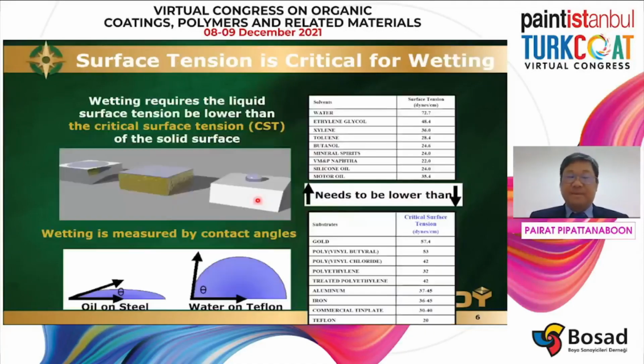This diagram tells you how the diluent or solvent has a surface tension in the unit of dyne per centimeter. And what is the critical surface tension or CST of solid surfaces, from gold, aluminum, iron. It is an example of some products, solvents and solid surfaces you can see from the market. Let's take the example of aluminum surface. It has surface tension of about 42 dyne per centimeter. To coat on the aluminum surface, I need to compare silicone oil, which has 24 dyne per centimeter surface tension, with water, which has about 72 dyne per centimeter surface tension.